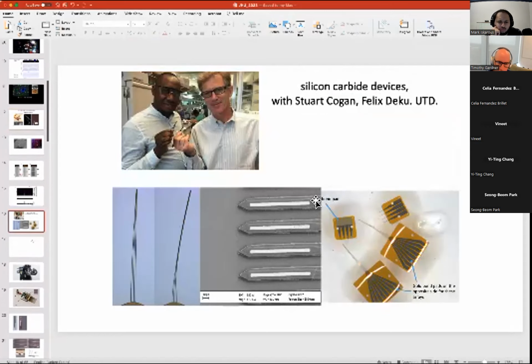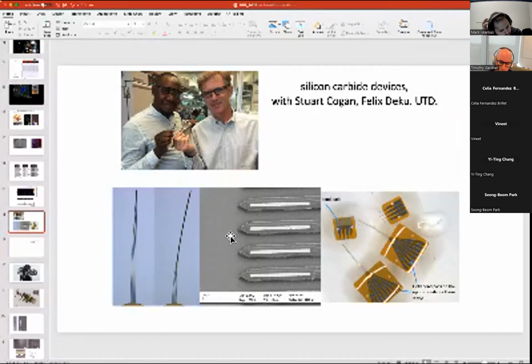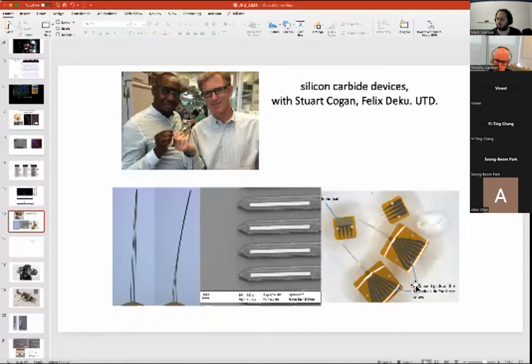And so that led us to collaborate with Stuart Cogan's group at UT Dallas, where, with the support of the NIH, we developed a concept which was silicon carbide needles that had very similar modulus and geometry to the carbon fiber electrodes that we had been implanting, but these could now be microfabricated in a clean room using more of a high throughput scalable process. And that work is still in development.